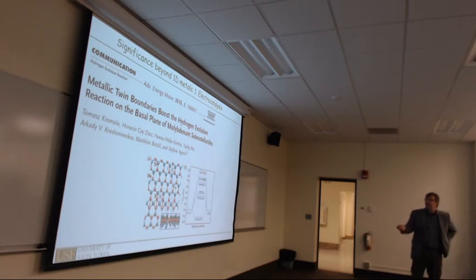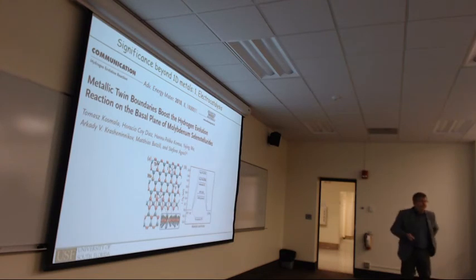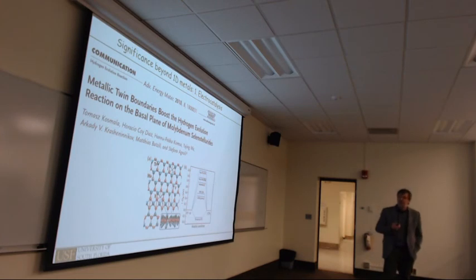If you have perfect molytelluride, then you can have the hydrogen either diffusing over the top or the top of molybdenum, but in either case you have a large barrier for hydrogen evolution. But if you have twin grain boundaries and you go next to it, the hydrogen likes to go into the interstitial, and that lowers the barrier for hydrogen evolution significantly. So by introducing these twin grain boundary loops, you can increase the activity of molytelluride, for example, where we have to say that tellurides are probably not really practical electrocatalysts, but it's just a demonstration that these grain boundaries can enhance activity.